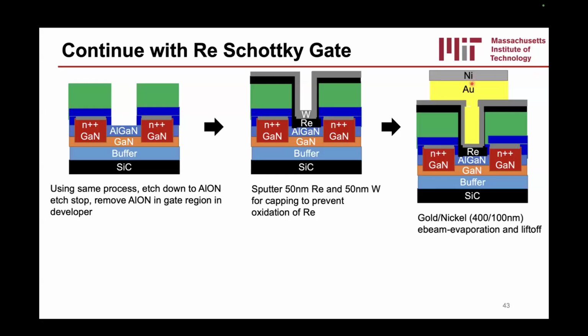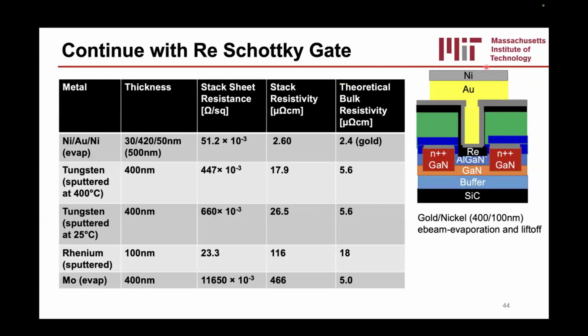The reason why we wanted gold and nickel here is mostly from a resistivity point of view. It turns out the gate resistance here is a really important parameter for RF devices. And if you look at gold resistivity, what we measure is 2.6 microohm centimeter. Theoretically, you get about 2.4 microohm centimeter. And all the refractory metals, at least that we can deposit in our clean room, are at least 10 to 20 times higher resistivity. Like for instance, moly is about 200 times higher, even though theoretically it should only be 3 times higher. So although gold in practice is not the most refractory, it's very good at being a very low resistivity metal. And we find that it works at 500 C.